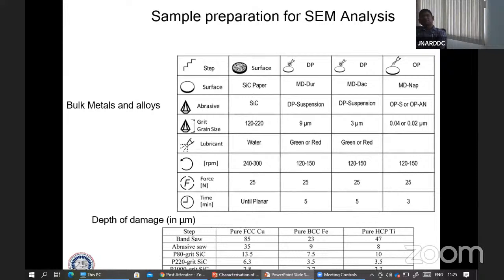Suppose you want to analyze any inclusions or precipitates, like any bigger size materials, you can use the samples for SEM analysis as they are. Or if you want to see some grain sizes and so on, then you have to etch it with the proper etchant.